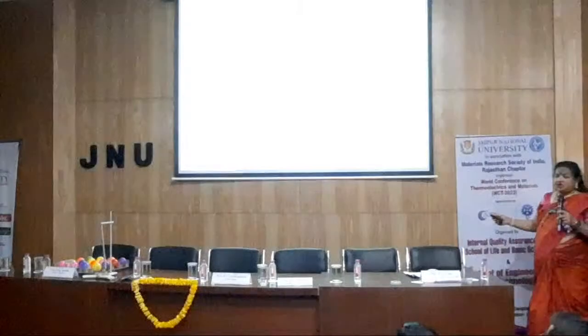So all samples, like if you have a powder or a tissue, can be freeze dried using liquid nitrogen. If it's something biological like blood or tissue, you have to digest it in concentrated acid, HNO3, and then you can micropipette 5 to 10 microliters onto a target and go to a proton beam for irradiation.